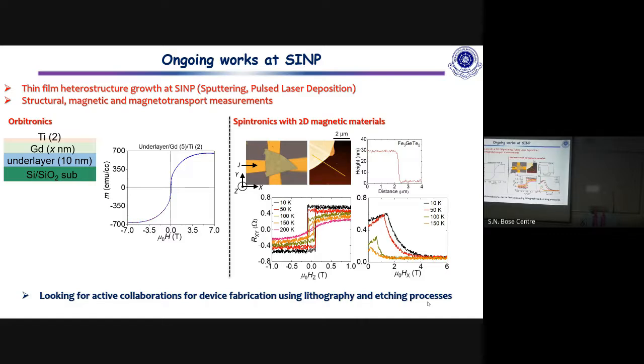But the anisotropic magnetoresistance, for our case, doesn't explain the behavior that we see. There is no other source of such a high signal. This is the only thing that you can see here. So for magnetic anisotropy... No, but we also have the texture, right? That is what I'm talking about. Yeah, this texture is giving rise to the anisotropy. So the magnetic anisotropy.